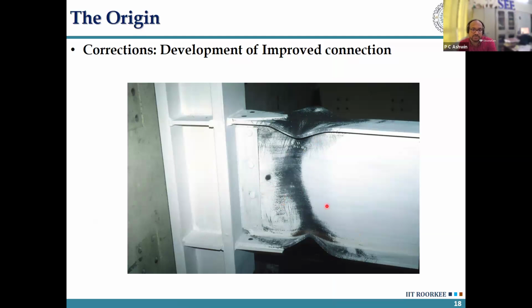So during a test, what we do is we whitewash, we put a white paint over it, and you know that when a material yields, it has a permanent deformation set into it, right? Once the material crosses the yield limit, a permanent set comes in. So wherever the white paint has gone off is where a permanent set has already come into the structure and into the member. Now, what you see here at the top, the flanges, is a phenomenon known as local buckling. Local buckling is inevitable because when you have an earthquake, this beam is going up and down. There is a permanent deformation that comes in these flange members. And when these elongated flange members go under compression, local buckling is bound to happen.